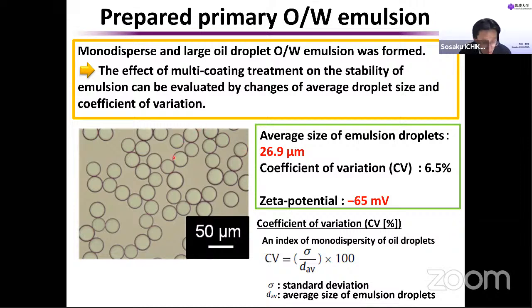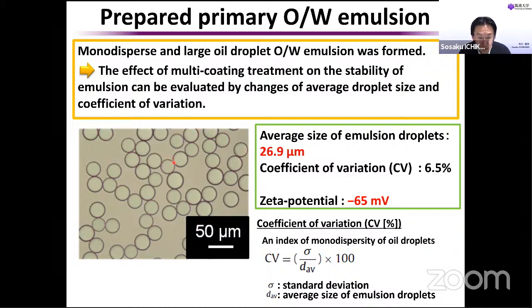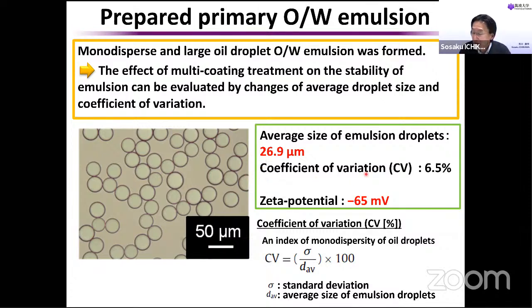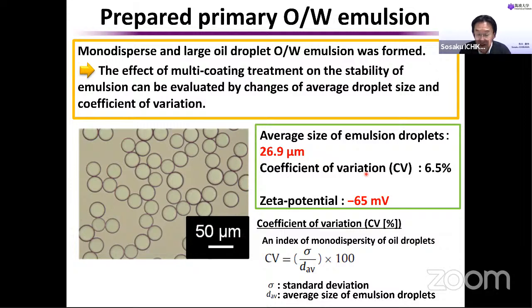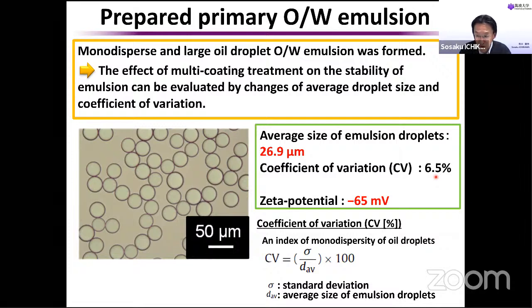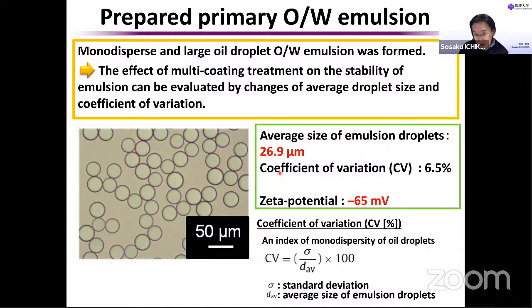This is a microscopic image of the oil droplets made by microchannel emulsification. The average size is around 27 micrometers. The coefficient of variation, an index of the dispersity of the oil droplets, is only 6.5. Normally, a CV of less than 10% is called a monodispersed emulsion.